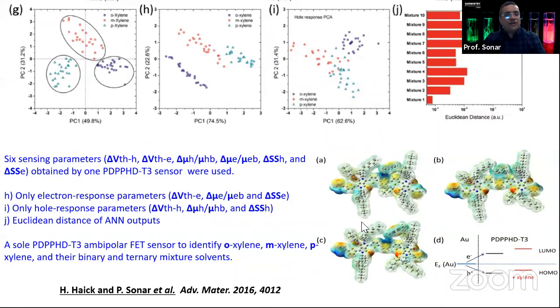And using some principal component analysis, this PC1, we can distinguish the 3 isomers of xylene, which are ortho-xylene, para-xylene, and meta-xylene. Xylene has a benzene structure with 2 methyl groups. If the second methyl group is next to the first methyl group, it is called ortho, then on the 2nd position meta, and then the 3rd position para. So it is very critical to analyze structurally very similar analytes with a sensor like this. And we demonstrated for the first time that even with very structurally similar isomers, we can still identify the difference. That is really a very nice outcome that came from this collaboration.